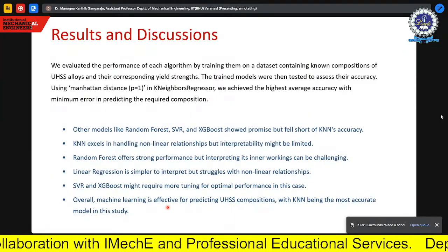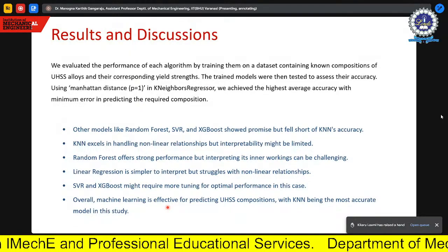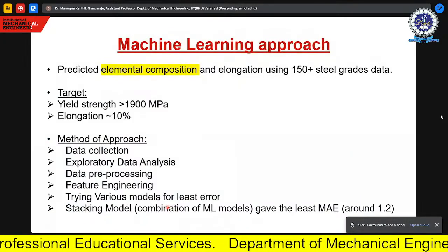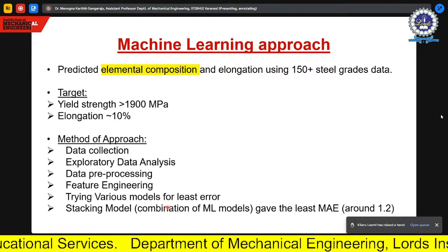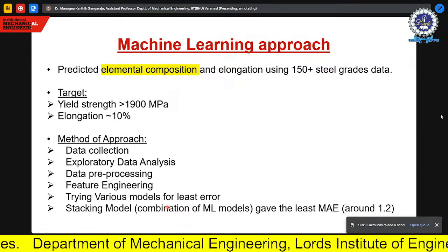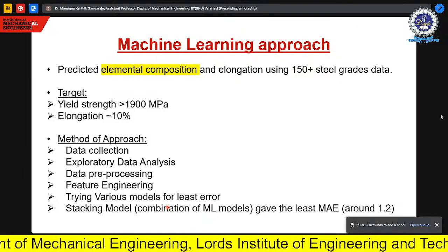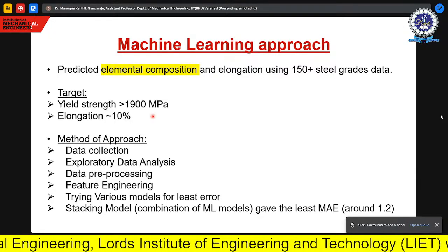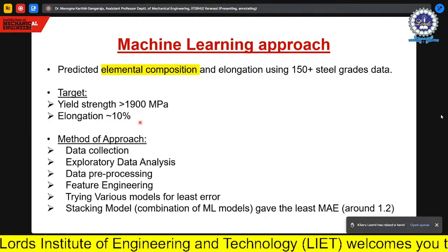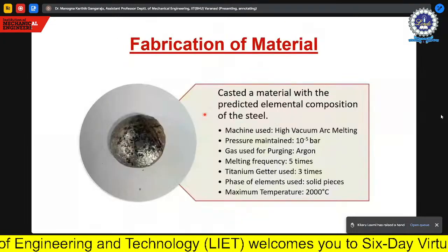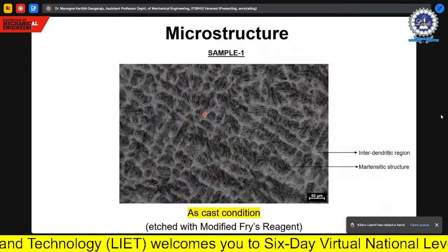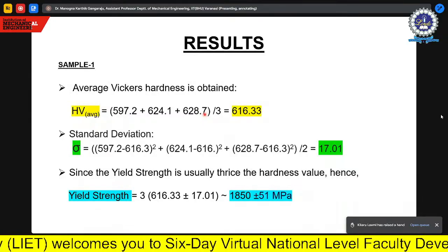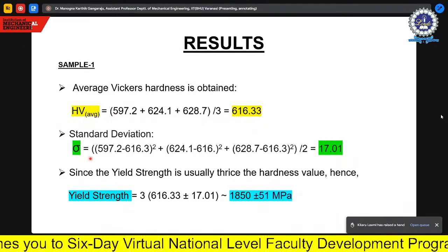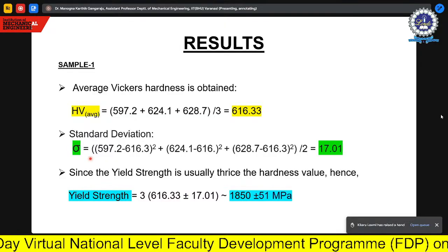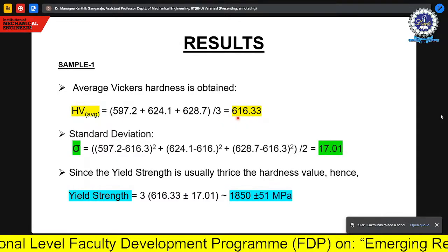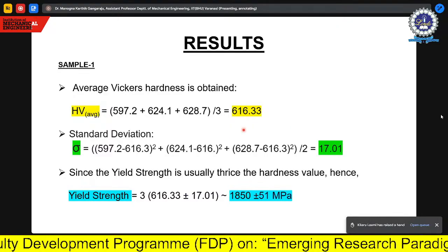Our observations are that we were able to develop this model, and with the model we were able to get some compositions. To validate whether the composition from my machine learning model really gives this experimental data, we developed this composition targeting yield strength greater than 1900 megapascal and elongation of 10%. This is our target, but we will see how we are able to achieve it. We melted this material, did some microstructural analysis, and have hardness values here. Since the material that we developed is very small, we could do only a hardness survey. The melted material has hardness close to 600 Vickers hardness.